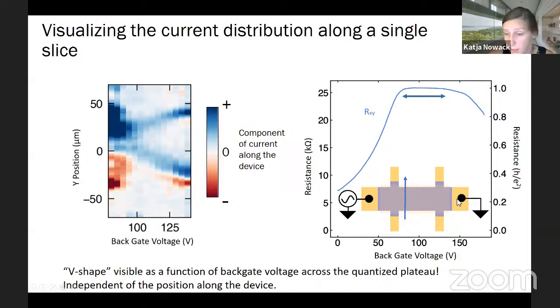If I call this the y direction, then this would be the x direction. So what is plotted is the x component of that current density. And we observe this interesting V shape as a function of backgate voltage across the quantized plateau. We see current starting out in the bulk of the sample, but as we tune the backgate voltage, it's bifurcating or branching in this way. We can also say that this exact shape is independent of where exactly we take the slice through the sample. And we've observed this on two different samples made from the same film, so it's not a feature of the exact location nor of this exact device. But nowhere throughout this plateau do we see the current concentrate along the edges of the device.